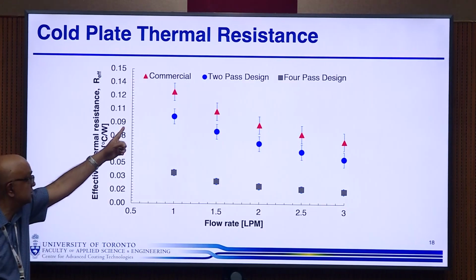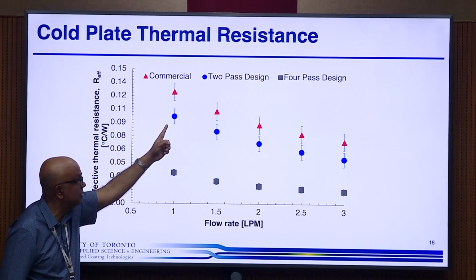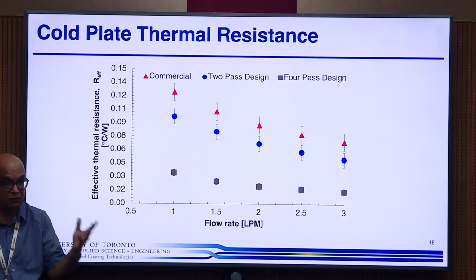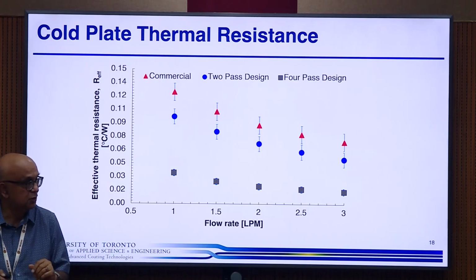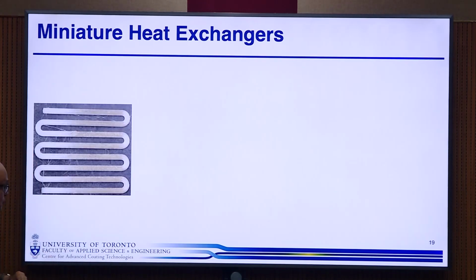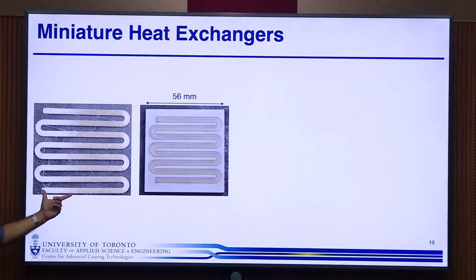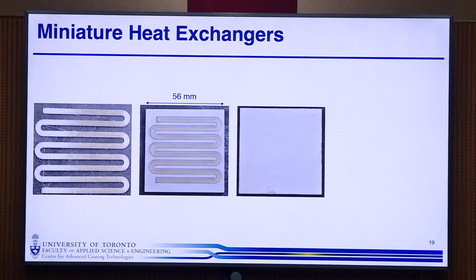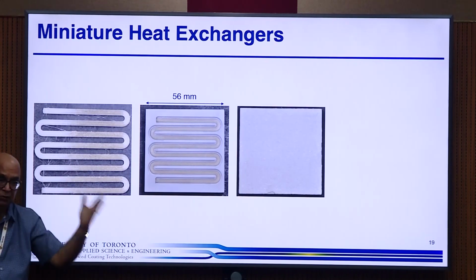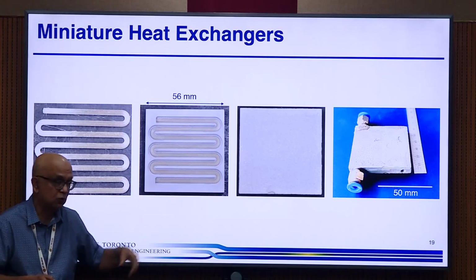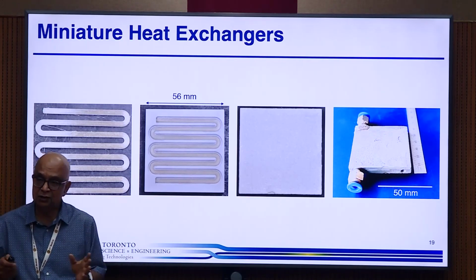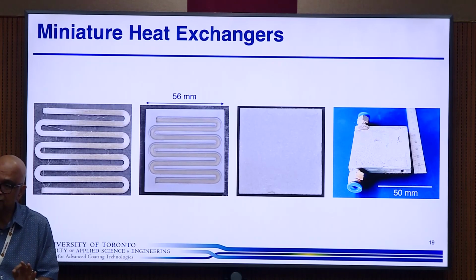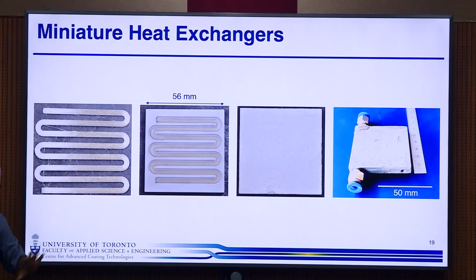And when you test it, this is the thermal resistance of a commercial one, this is the 2 pass, this is the 4 pass, and we've improved it. So this is nice. But now you can really make complicated ones. So this is a miniature heat exchanger. This thing is about 1 millimeter wide. The whole thing is about 56 millimeters square. We spray it on one side, we do the same thing on the other side, and you've got a tiny heat exchanger, very efficient. We've tested these, and so you can make very effective ones. So we can do very complex internal channels using this sort of technique.